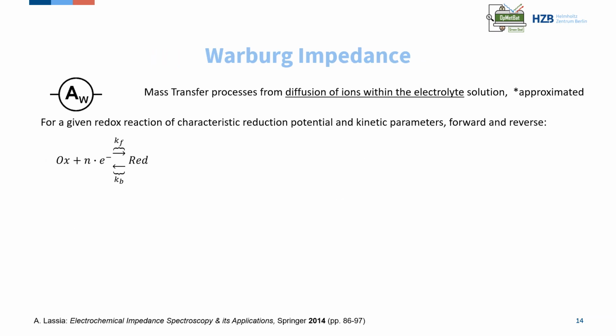For the case of redox reactions at electrode interfaces in which mass transfer of ions has a significant contribution, an additional Warburg element needs to be included in the equivalent electrical circuit to consider the diffusion of ions within the electrolyte solution. The Warburg element implies that the charge transfer is also dependent on the diffusion of the redox active species. The treatment of this element can be more complicated and tedious, and is also described with kinetic parameters of